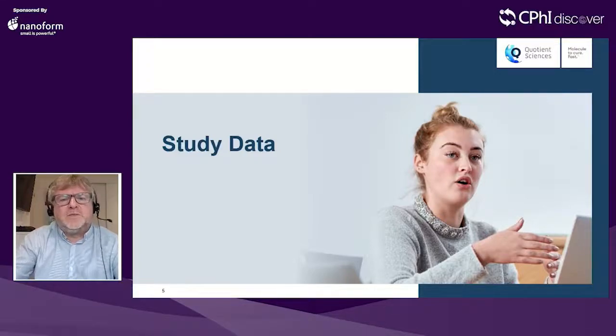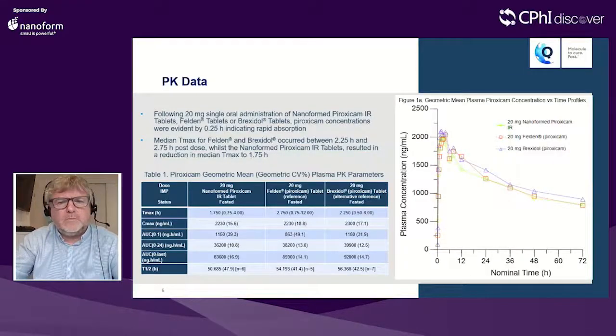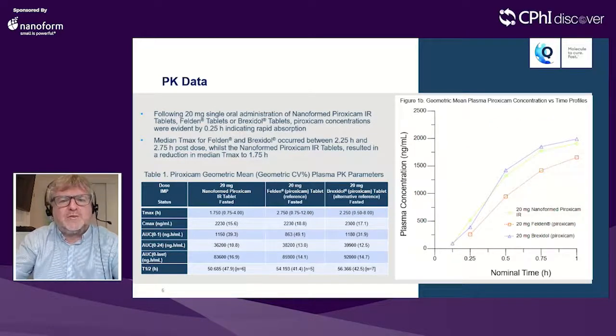So let's look at the data from the study now. As can be seen in Figure 1a, following dosing of all 3 20 mg products in the study, rapid absorption was evident, and if we zoom in on the first hour following administration in Figure 1b, you can see that the nanoformed piroxicam immediate release tablet is absorbed more rapidly than the standard Felden reference, and indeed the median time to reach maximum exposure was faster for the nanoformed piroxicam immediate release tablet than both reference products.